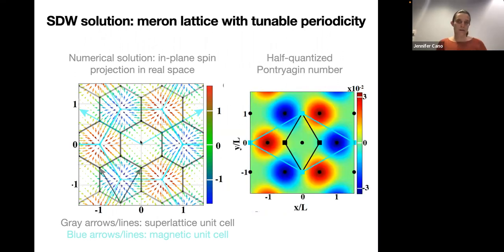And if we compute what's called the Pontryagin number, which is basically the Skyrmion number, we see that it's actually quantized to be +1/2 and -1/2 in all of these different triangular regions. So these things are really like half Skyrmions that are interspersed with each other in just the right way to be stabilized. And so I think that this pattern is a compromise between electrons wanting to sit in the minima of the potential, but they also want to have the spin momentum locking from their kinetic energy. And so this pattern has a little bit of both of those things.